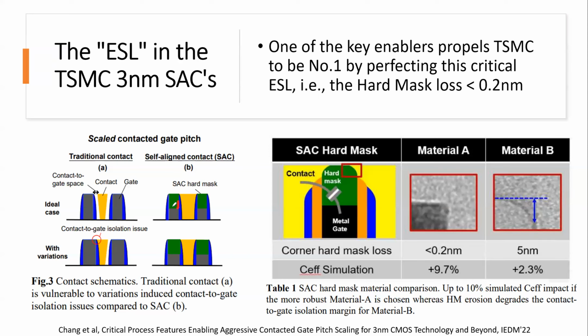So what they did is put a hard mask to protect it, a nitride, okay, or some kind of nitride, as long as you can put it inside. Nobody exactly knows what material TSMC put here. I think they probably work with TEL or Lam or Applied Materials to deposit the hard mask. And the key is to make it rectangular, okay, versus a round one. This minute difference is enough to change the C effective, the capacitance in this structure, right?